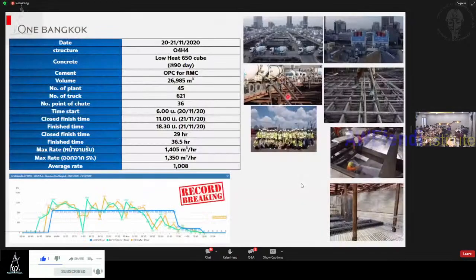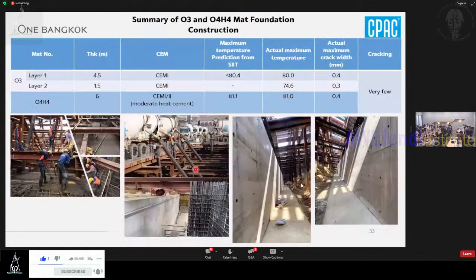The summary. So we have cast and achieved O4H4 for the mat foundation with 60 MPa. And you can see the volume here, the number of plants supplying the concrete, number of trucks, number of chutes. We spent around 36.5 hours casting continuously. And the max rate of supply is around 1,405 cubic meters per hour, and average around 1,000, something like that. So it's our pride project here. And after casting, we observed some actual cracks, but very few. So it's acceptable for our party.